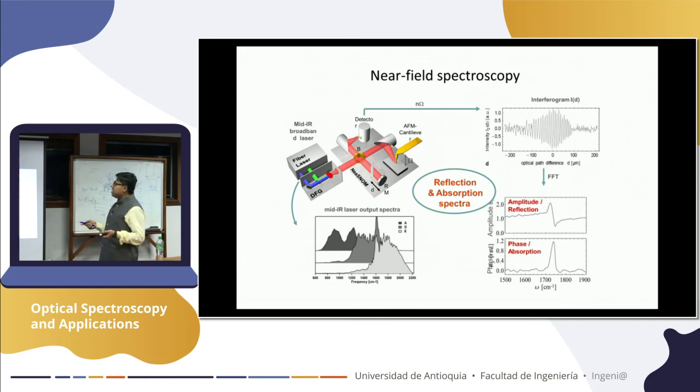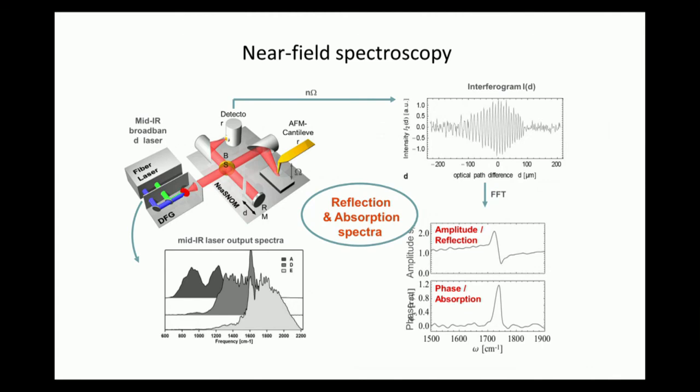The point is that now you put a Michelson interferometer into it, so you do an interferogram, same thing. Instead of directly taking infrared light coming to a sample, you take the scattered photons and that makes the interferogram, which we did on day one, and then do the FFT to get the spectrum back. That gives you a much higher signal to noise ratio. And the key point here is that you can also change the source. You can change your laser source and have wavelength dependence.